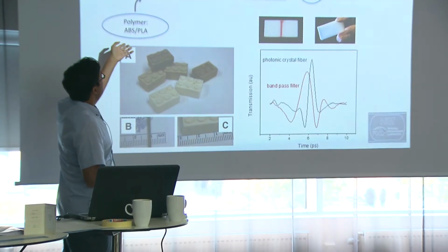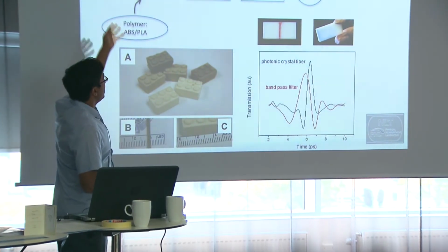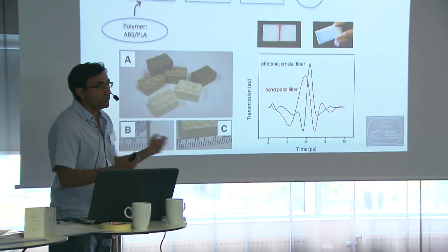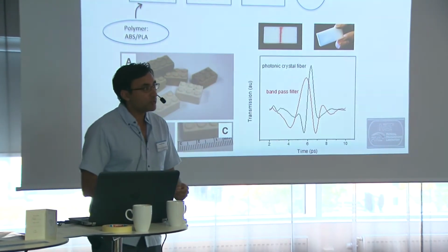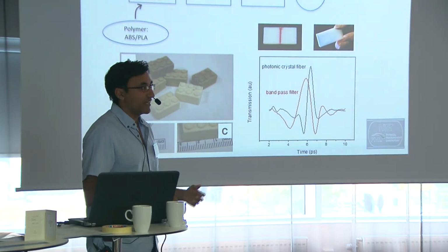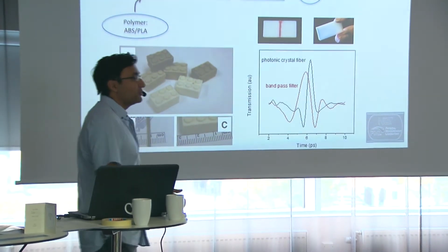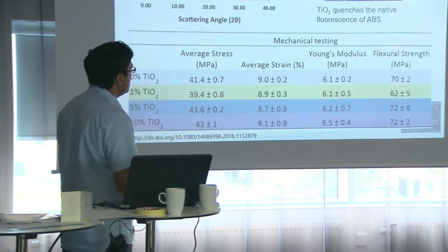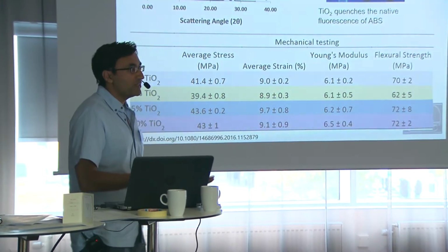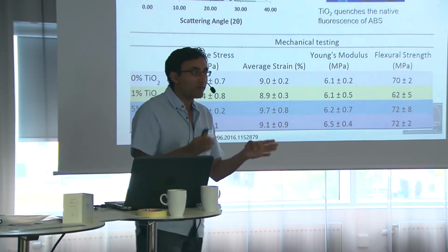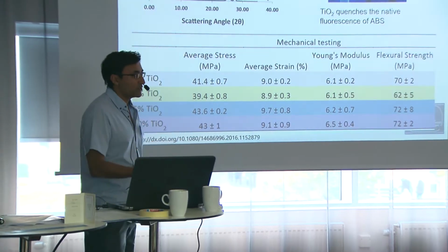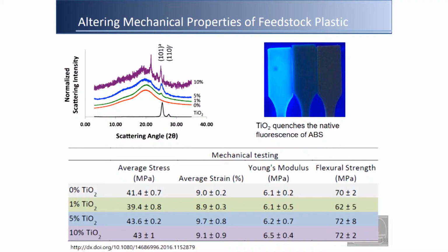So you start with ABS or PLA. You mix in nanoparticles, you blend them, and you extrude a filament that you can then use for printing. Of course, you're trying to find materials that will actually print and that won't degrade. So the first thing we did was we were at least smart enough to start with a more robust system. So we started with TiO2 nanoparticles, mostly because they're harder to destroy.